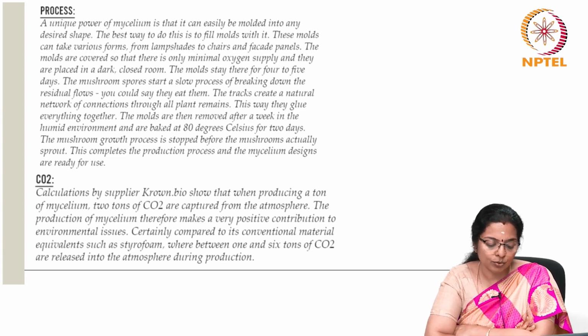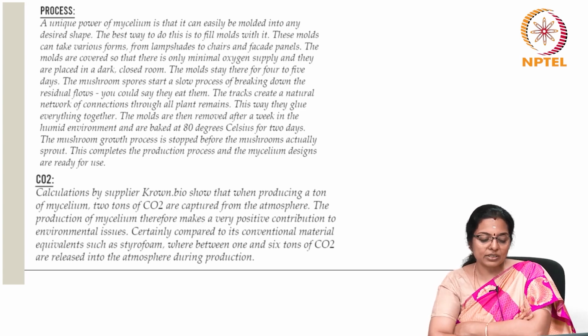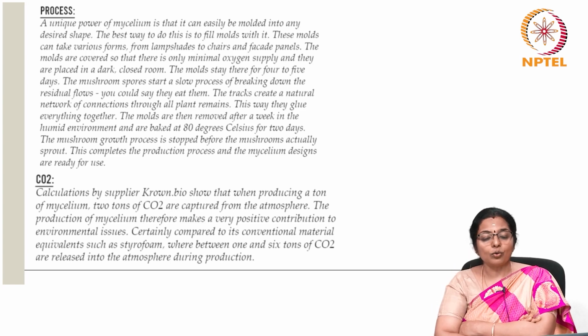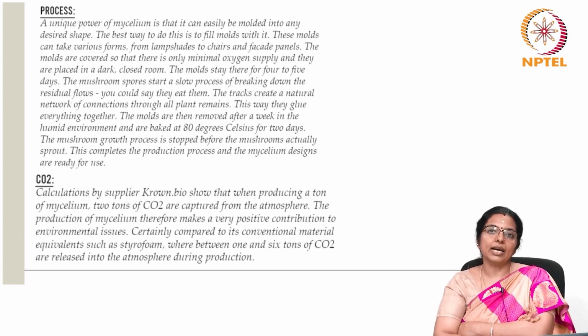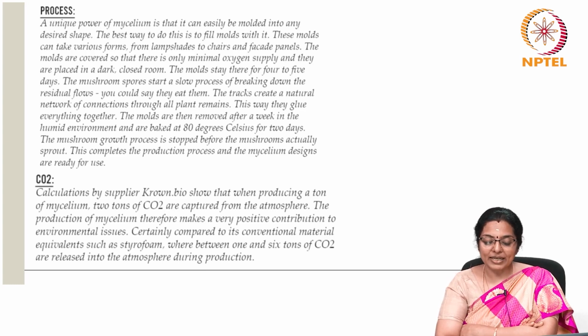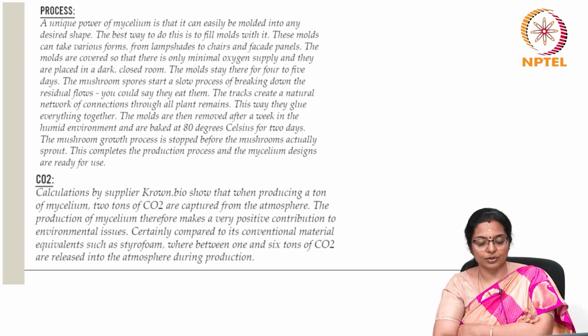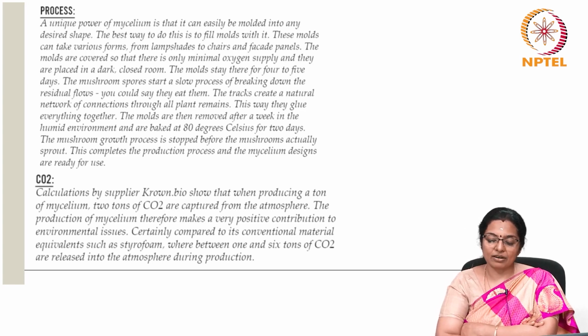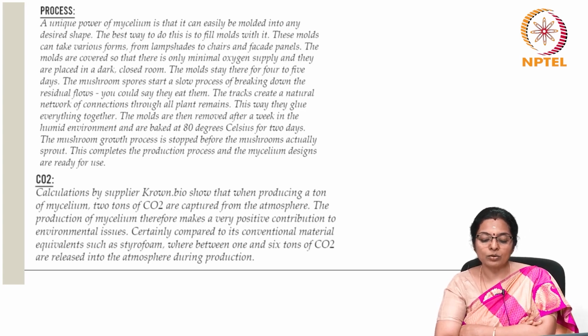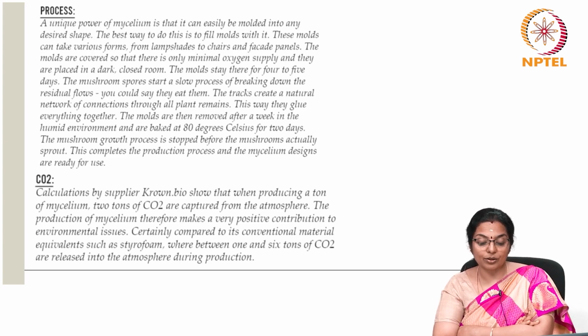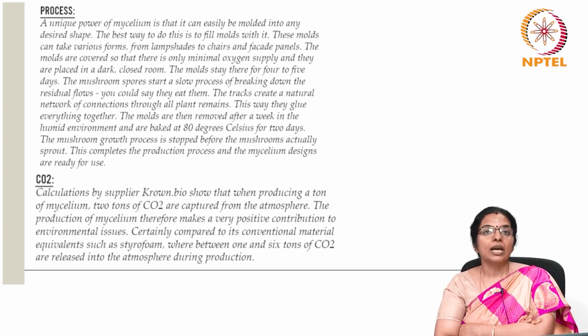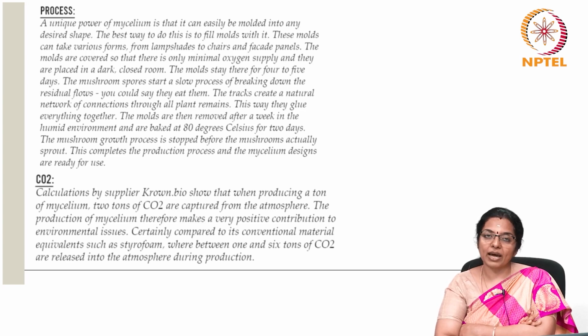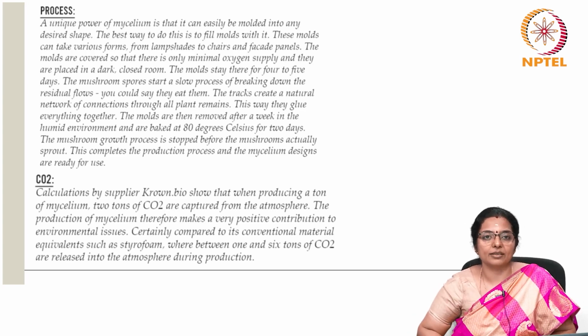If we look at the CO2 calculations by the supplier Krown.bio, it shows that when producing 1 ton of mycelium, 2 tons of carbon dioxide are captured from the atmosphere. The production of mycelium therefore makes a very positive contribution to environmental issues. Certainly, compared to its conventional material equivalent such as styrofoam, where between 1 to 6 tons of carbon dioxide is released into the atmosphere during production. It seems that mycelium bricks or panels are extremely green materials.